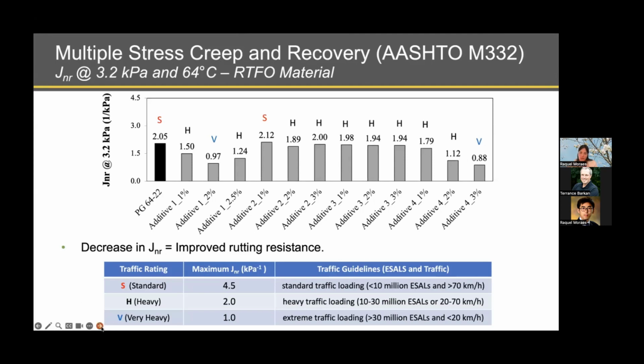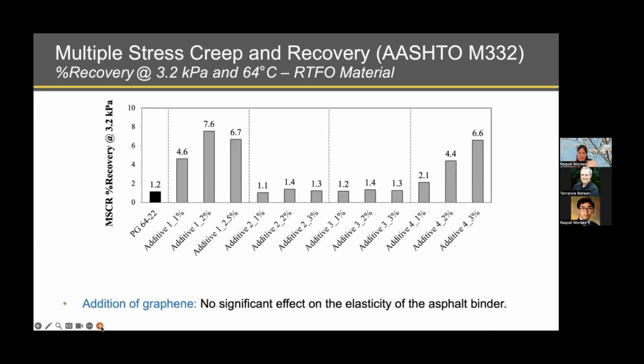So as we saw previously, for the high temperature performance grade results, we saw a slightly increasing the rutting resistance of the binders after the incorporation of the graphene. And then the other parameter that is obtained from the MSCR is the percentage recovery. So you can see here, and as expected, we are not incorporating any elastic component with the graphene in terms of polymeric contribution. So we are not expecting that the graphene would significantly increase the elasticity of the binder. And you can see by these results.